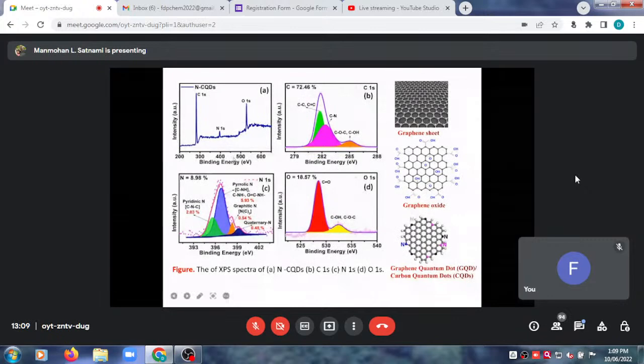Then what we did, we chose the different peaks of carbon, nitrogen, and oxygen and deconvoluted them. Deconvoluted means expanded. When we expanded, we found that among this peak, there are many peaks: 1, 2, 3. And with these peaks, the binding energies are here. On the basis of this binding energy, we characterize which kind of carbon is present in the carbon quantum dot. So this is C-C, C=C, C-N, C-O-C, and C-OH.